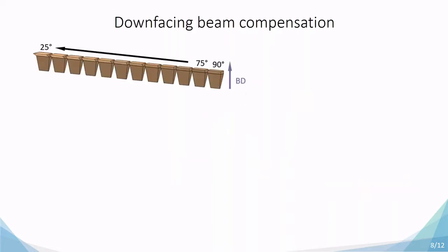To develop this down-facing offset, we printed one reference sample with vertical surfaces and several down-facing geometries with a down-facing angle varying from 75 to 25 degrees. This was done in titanium 6.4 with a ProX 320 from 3D Systems, with already optimized parameters for the down-facing region.